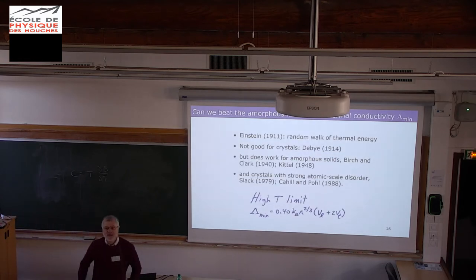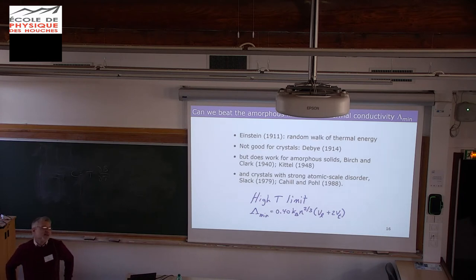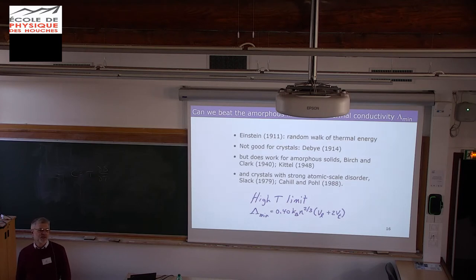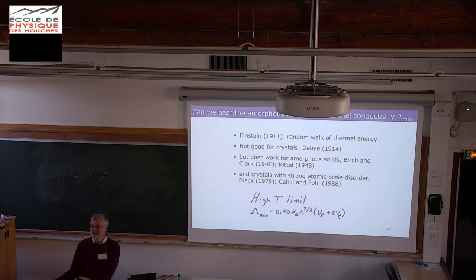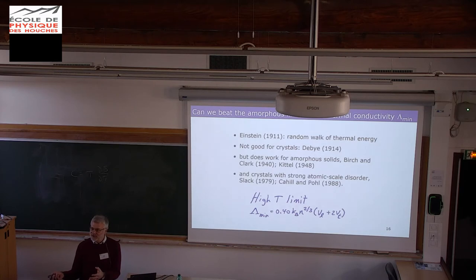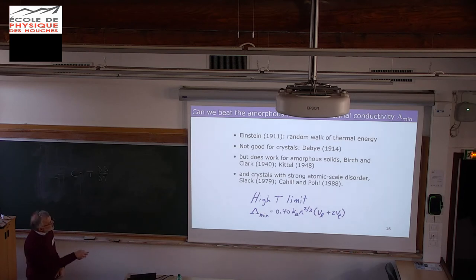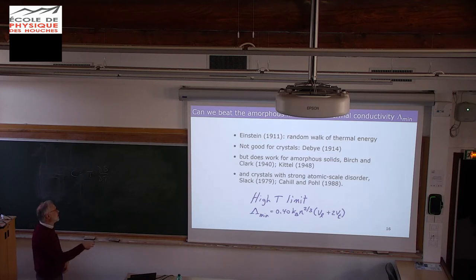My first problem is: can I beat the lower limit of what we call the amorphous limit, or minimum thermal conductivity of materials? The conventional wisdom about this starts with Einstein in 1911 — he was actually the very first person to write down a theory for heat conduction in a material. You don't know that because his theory is wrong. Debye gave the right answer the year later, in 1914 — wrong for crystals, but maybe correct for amorphous materials. There's a long history — Birch and Clark were geologists, this is Charles Kittel whose name you know from his textbook, and Glenn Slack. The bottom line is that in the high temperature limit, the minimum thermal conductivity is a numerical factor times k_B, times N^(2/3) — the atomic density to the two-thirds power — times something like an average of the longitudinal and transverse sound velocities.